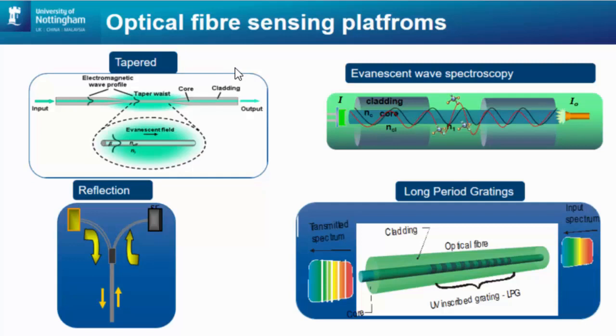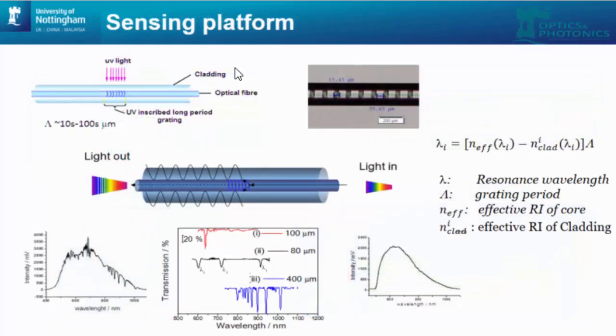The other way of creating sensors is so-called grating sensors, and they provide wavelength encoding information. In this work, I will present long period gratings. So what is a long period grating? You create a periodic modulation of refractive index inside the core of an optical fiber, and the typical way of doing it is you expose silica optical fiber to UV patterns, and because of the photosensitivity, it induces a refractive index change in the area where it was exposed to UV light. So you can see this pattern, this structure here.